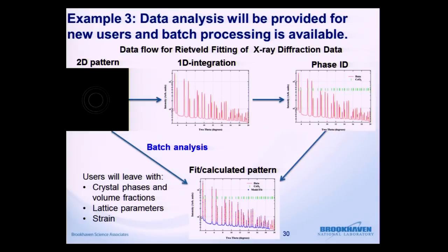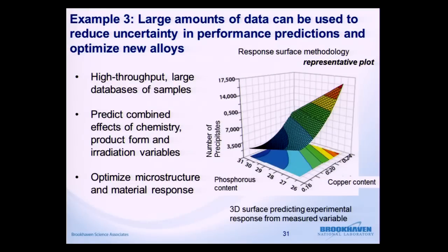So with batch processing, our users will leave with this information, which is what they really want. So they won't just be leaving with these images from the detector, they'll actually be leaving with the information that they need for their scientific models and theories. And for us, this means that we can use the large amounts of data that we have to reduce the uncertainty in the performance predictions and also to predict interactions between those many variables that we outlined at the beginning. So we'll be able to predict the combined effects of chemistry, product form, and irradiation variables on the response of the material. So this will allow us to really improve the predictions and understanding of the performance and to optimize the microstructure and the conditions for the operating conditions.